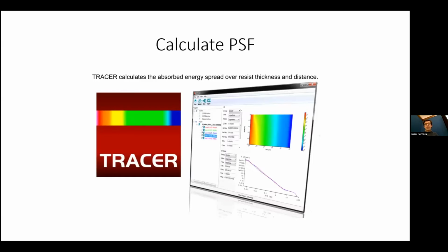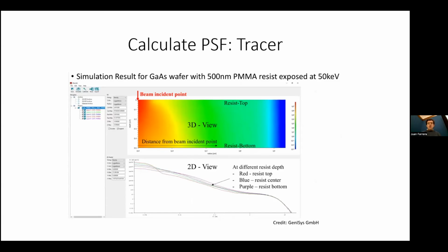But people have been developing software to correct for the proximity effect for a pretty long time. To calculate the PSF here at MIT.nano, we have this program from GenISys called Tracer. This allows you to very quickly define your resist stack and your substrate and obtain a point spread function. So here's an example. And you have a three-dimensional view of the energy deposition. And there's also a two-dimensional view, which are slices at different heights.